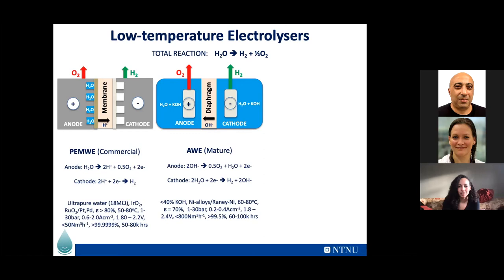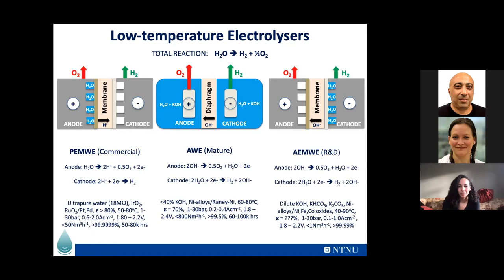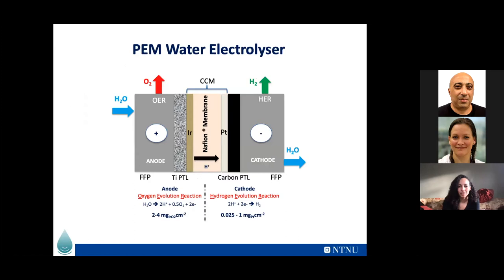And then we have another technology which is, I would say, still at research and development stage, based on anion exchange membrane water electrolysis, combining the pros of the two other technologies, the PEM water electrolysis and the alkaline water electrolysis. In that technology, you can use dilute KOH, or potassium hydroxide, or any type of carbonates. And you also use non-precious metals like nickel, iron, and cobalt oxide, for example. So I'm going to focus here on the PEM water electrolysis.